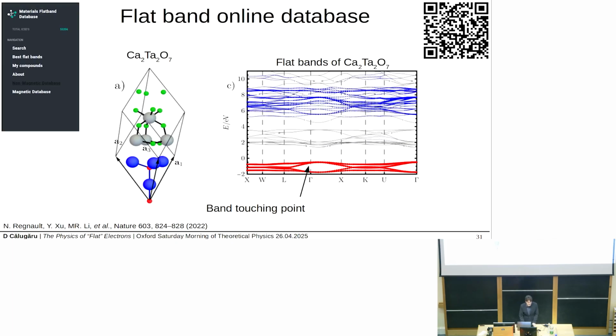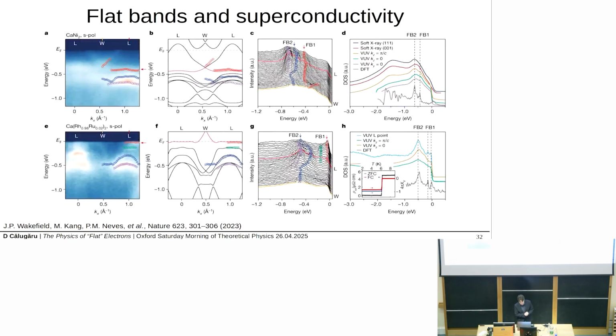My personal recommendation is once you go to the website, you should go to this best flat bands section, because these have the cleanest flat bands. And actually, another recent experimental paper, this time from MIT, they took one of the compounds that was highlighted in this database. The compound looks something that you would never write in a chemistry exam. Is calcium nickel 2, right? And the interesting thing about this compound is that it actually has flat bands close to the Fermi level, right?